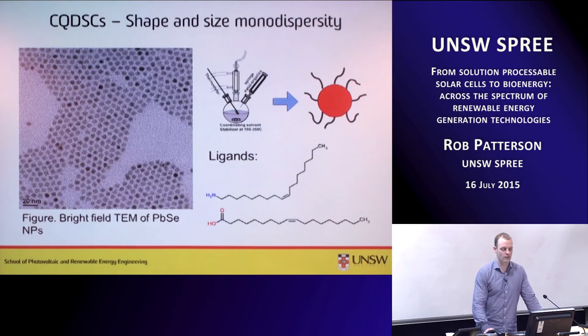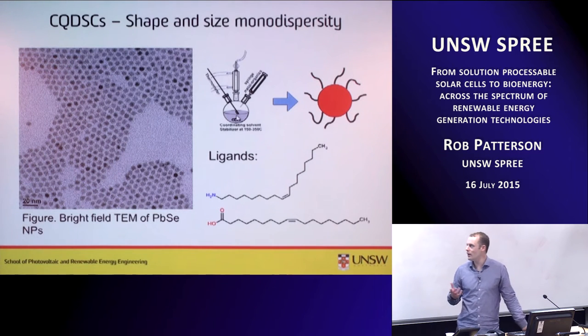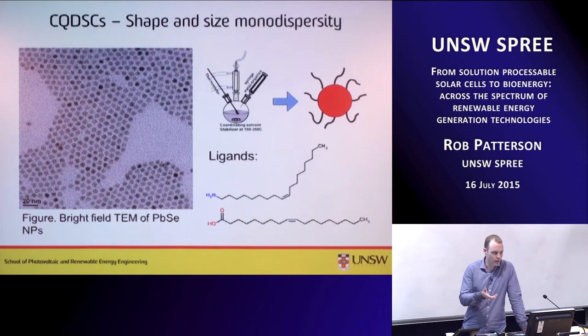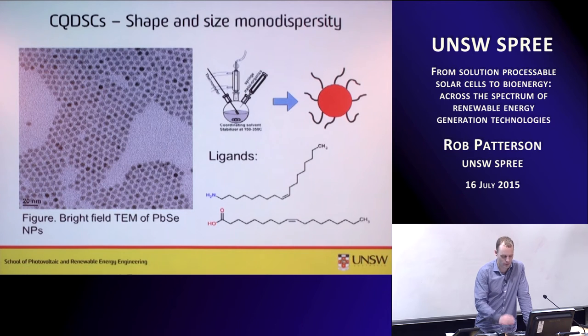Something for a general audience, again, that I find quite miraculous about these materials is that if you mix up your chemicals right in a three-neck flask like this, you can create particles that have very, very strict tolerances on their size and shape. So these are essentially spherical nanoparticles, and all of them have a size which is within a few nanometers of each other. And there are billions of them. This kind of uniformity from a solution processing approach is just interesting to me. What you end up with is nanoparticles that have surface ligands. These ligands look something like this, long chain hydrocarbons typically, with the hydrophilic end stuck to the nanoparticle and the hydrophobic end dangling out in space here.